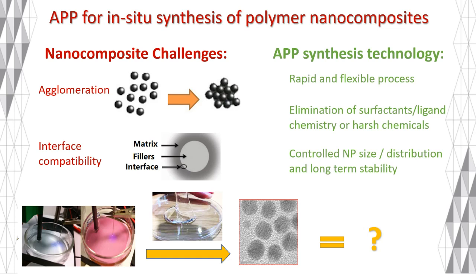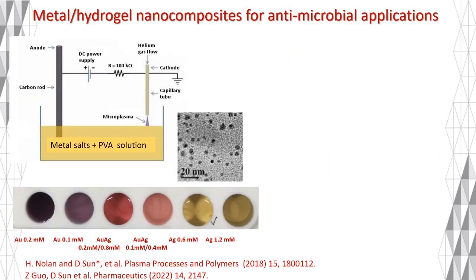To address these challenges, I have explored the potential of our plasma technology for exposing polymers or monomers and metal salt precursor together to the highly reactive plasma chemistry. And this together enables the electrostatic stabilization of a colloid system or the formation of a highly desirable interface chemistry within the composite system. So here this slide highlights the successful synthesis of a polyvinyl alcohol, or PVA, based nanocomposites incorporating gold, silver and gold silver alloyed nanoparticles.